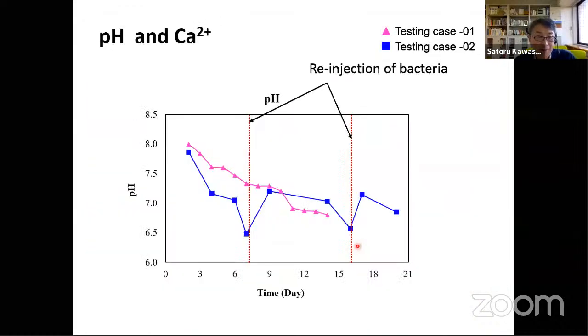And this one is the pH and the calcium ion change with time. Testing case 1 and testing case 2 are indicated like this. The testing case in blue: pH decreases with time. But 9 days later, it increased once again, because we added bacteria, re-injecting bacteria here. Then it decreases little by little. Then when adding bacteria, it increases. The pinkish color is the testing case where no re-injection occurred.